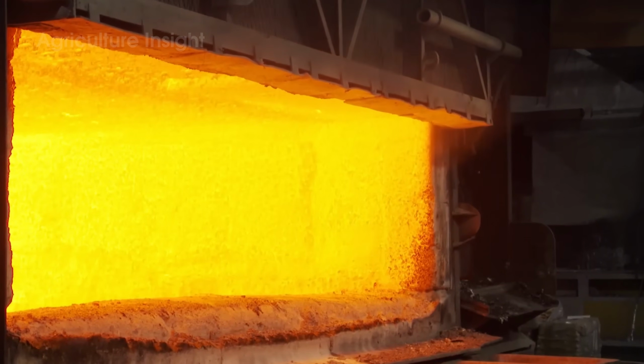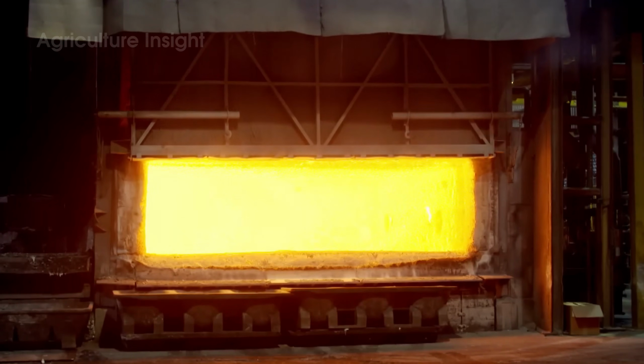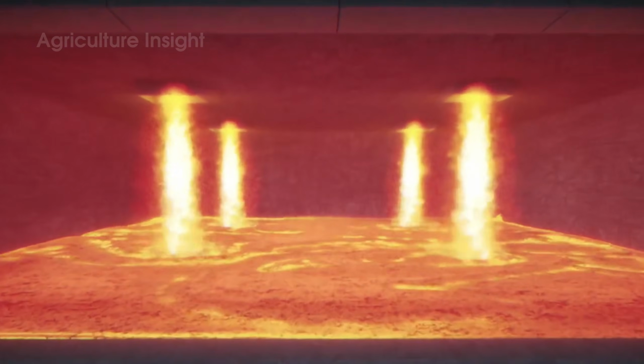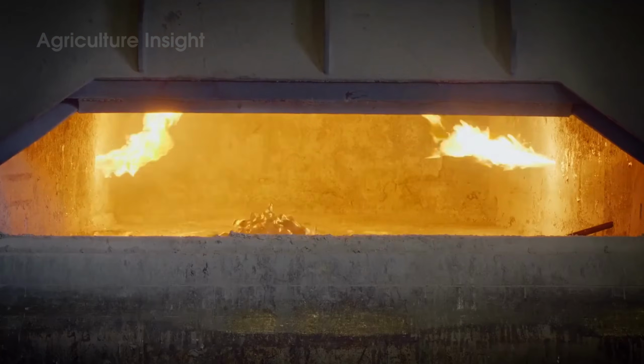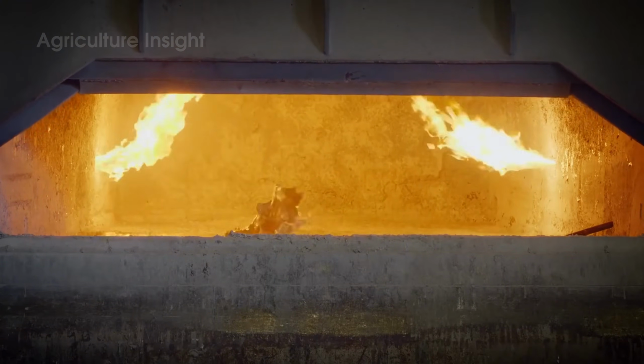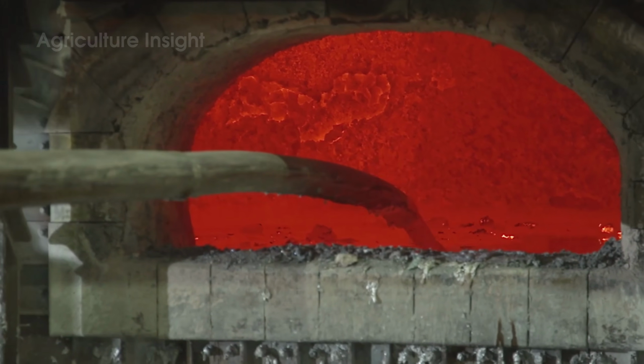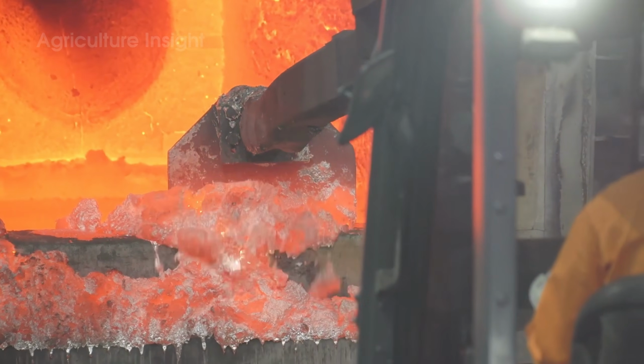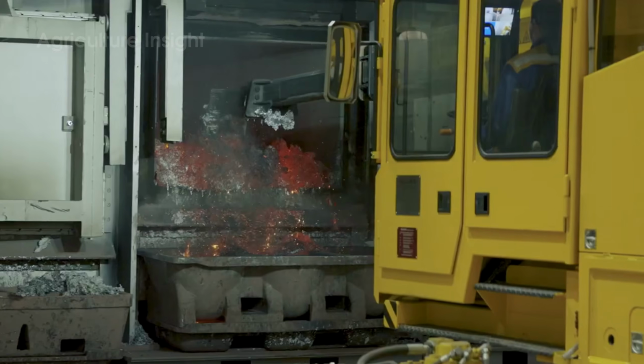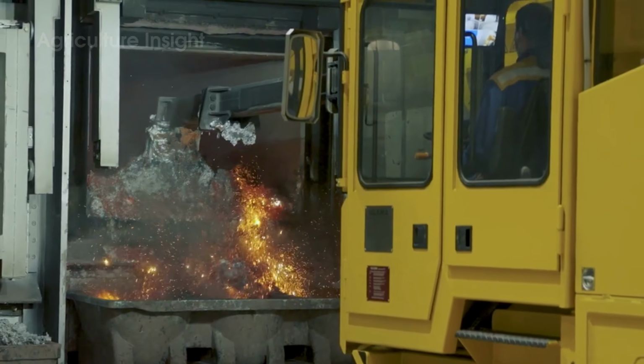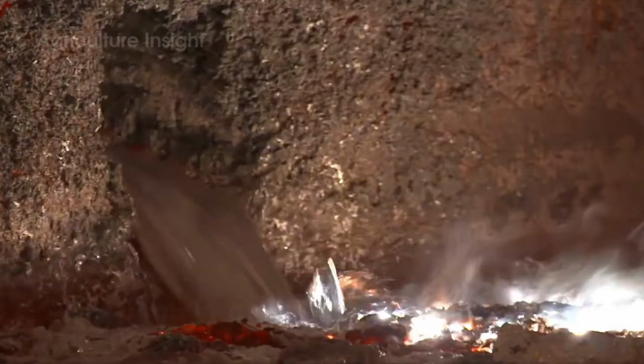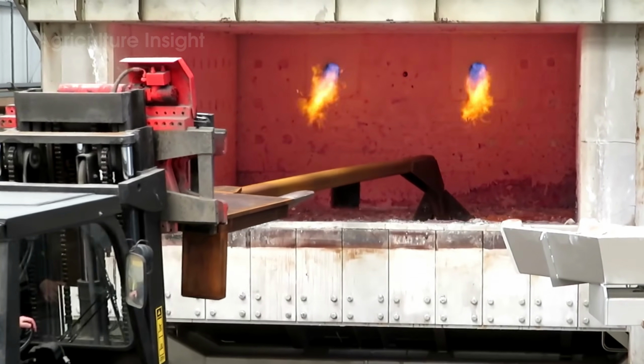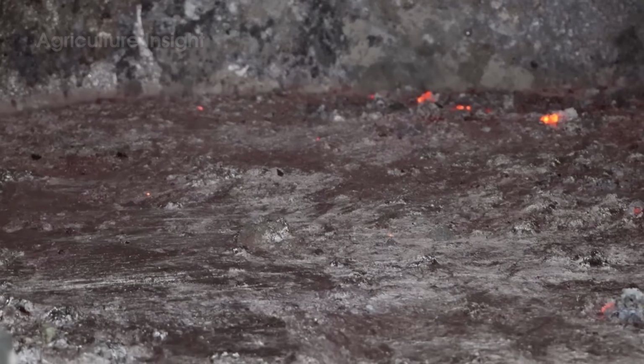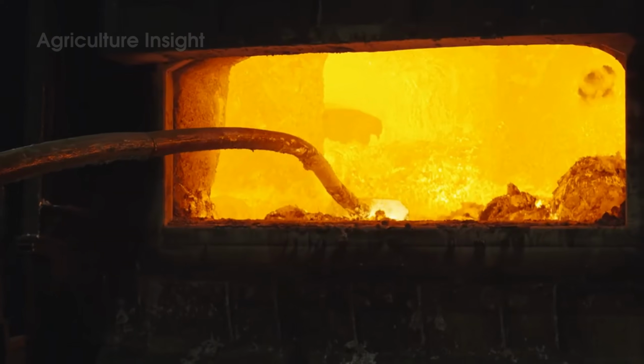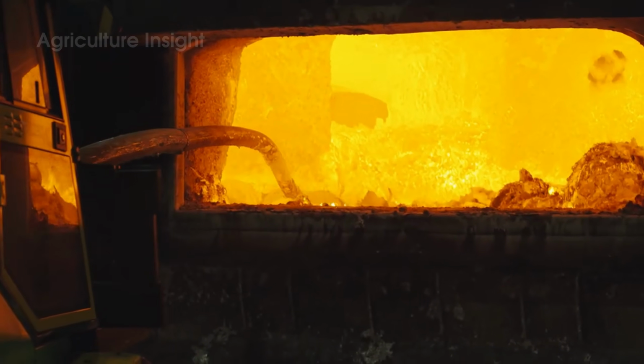During this process, aluminum is not simply melted, it also undergoes a form of refining. Lighter impurities such as residual paint, dust, and unwanted compounds rise to the surface as slag and are removed. At the same time, the high temperature fully breaks down old bonds, allowing the aluminum to return to a more uniform and purified state. Modern furnaces are designed to precisely control temperature and internal conditions, ensuring even melting, minimizing material loss, and preserving optimal quality. Once formed, the molten aluminum is kept in a stable state, ready for the next stages of production in the processing line.